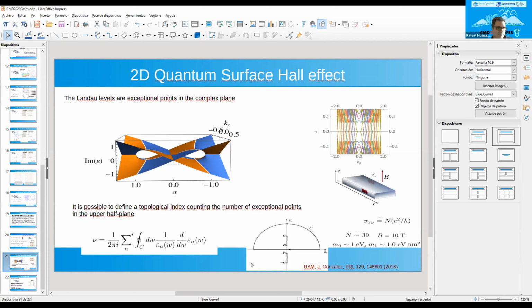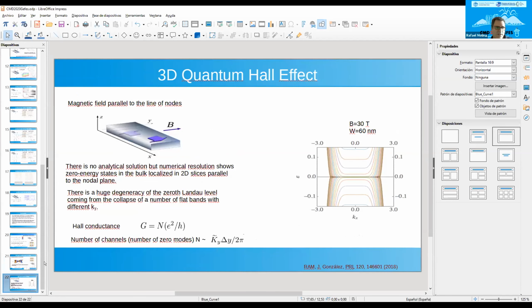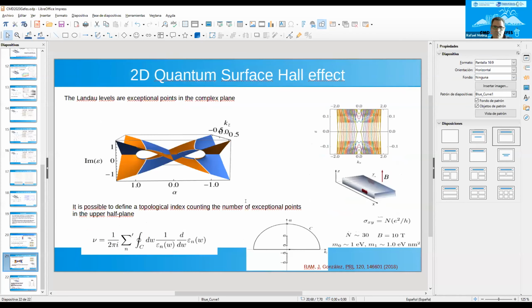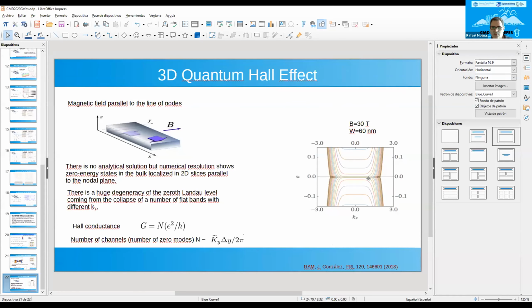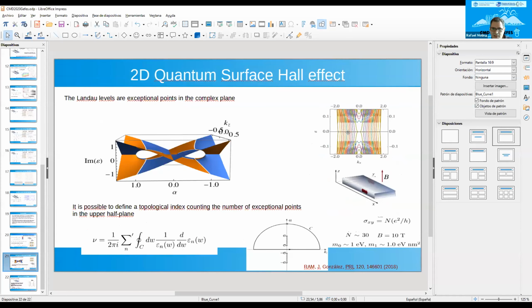Okay, thank you. I have a small question concerning the same topic. At the end of the day, in the case of the nodal line, you have to resort to numerics, right? Because if the magnetic field is parallel or perpendicular to the nodal line, the situation could be quite different and quite messy. Yes, but the numerics show that, for example, these are the numerics for this geometry, and these are the numerics for this other geometry, and in both cases you see a very large degeneracy of the zero mode that doesn't happen in the Weyl semimetal.